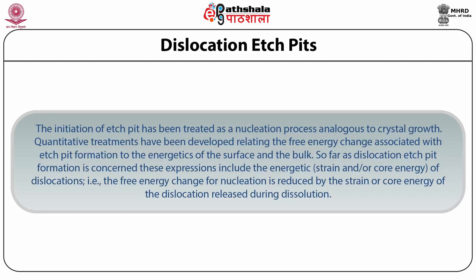Dislocation etch pits: the initiation of etch pits has been treated as a nucleation process analogous to crystal growth. Quantitative treatments have been developed relating the free energy change associated with etch pit formation to the energetics of the surface and the bulk. So far as dislocation etch pit formation is concerned, these expressions include the energetics, that is strain and/or core energy of dislocations — the free energy change for nucleation is reduced by the strain or core energy of the dislocation released during dissolution.